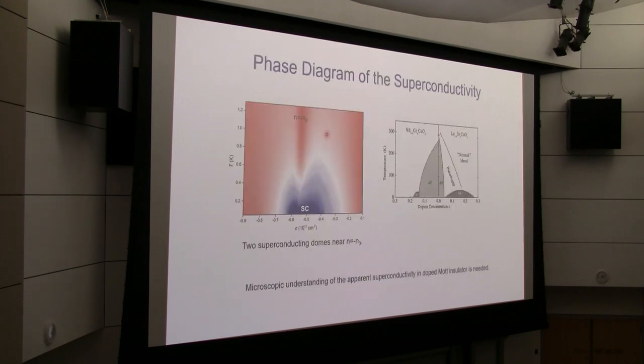We can also map out the region where we see signatures of superconductivity, and we found it is really clustered around the Mott insulator at n equal to n0. And it's reminiscent of what's seen in high temperature superconductors. Of course, we still don't understand the origin, so it requires a lot more theoretical and experimental work to really understand it.